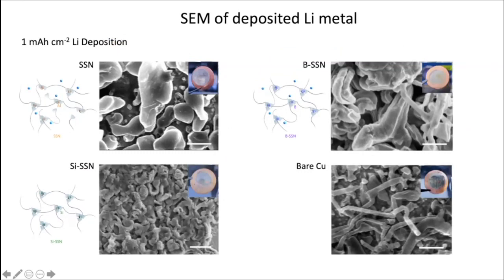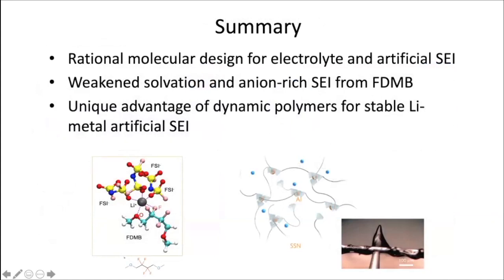Okay, and again, growth is this plate-like structure. So to summarize, here I've shown two examples of rational molecular design of electrolyte molecules and also artificial SEI. Our finding is that it's very important to tune the solvation of lithium in all of these systems. And the weakened solvation in the solvent we design, and also the incorporation of the anion into the solvation structure